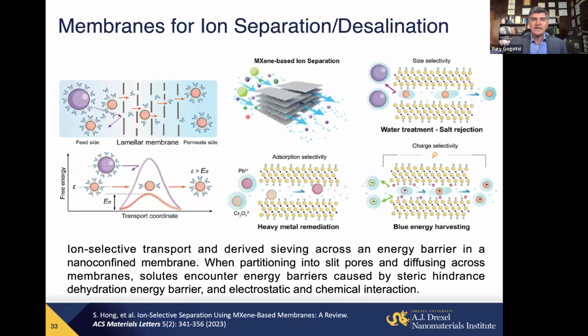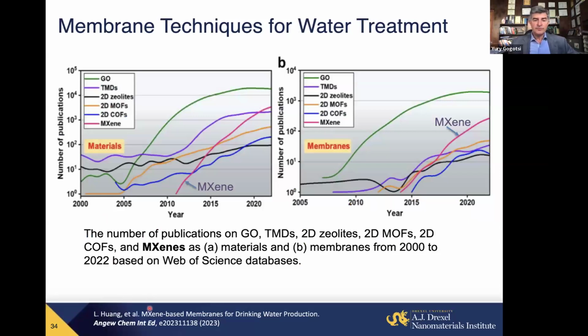Another big problem around the world nowadays is water purification and desalination. And again, because of these membranes, where we can use applied potential or simply spacing between the layers to sieve ions, one can do separation of ions, removing toxic ions, heavy ions, or desalinate water. Moreover, as you see from this analysis, published not by us, of MXene-based membranes for water production, MXene came into the field much later than any other materials. But based on the rate at which they grow, they already outperform greatly in number of publications all other materials but graphene oxide. But from the acceleration, you can see that in a couple more years they will be the dominating force in the field.